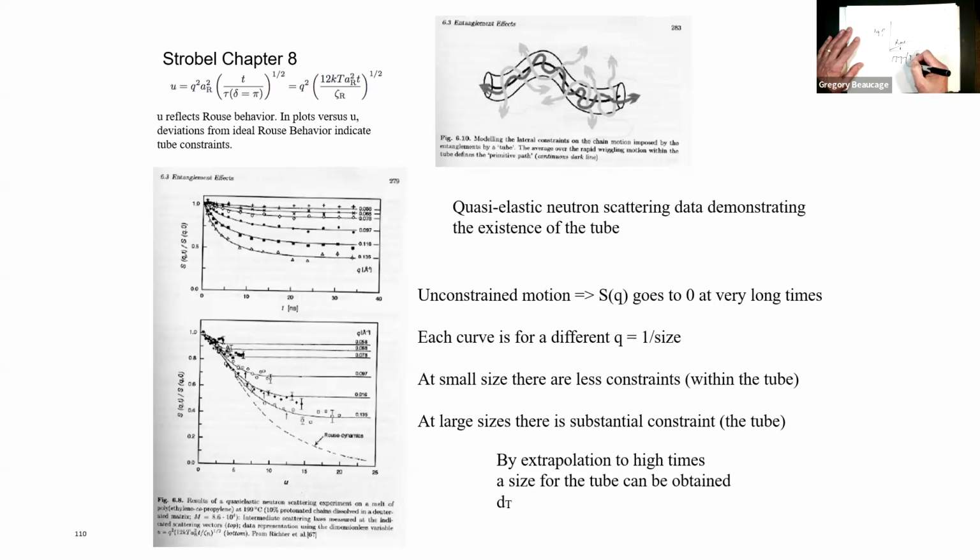Add another carbon, you get one more viscosity. Then all of a sudden, when you get entanglements, it shoots up to a 3.4 slope. So viscosity goes as molecular weight to the 3.4 power. And if you use this reptation model, you find out viscosity goes as molecular weight to the 3. It was missing the 0.4. For that reason, they wanted to get this 0.4.